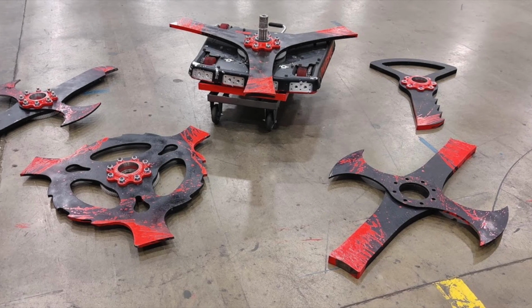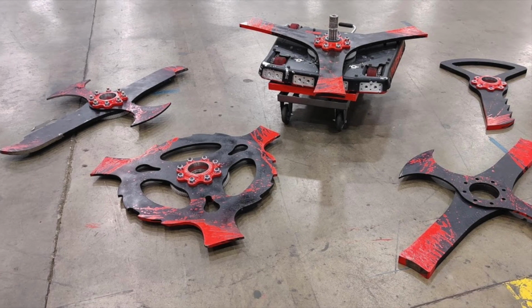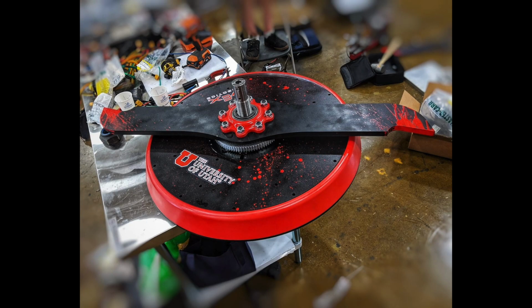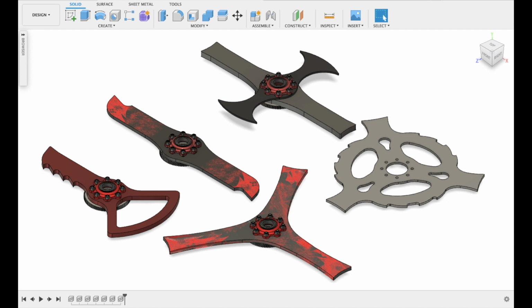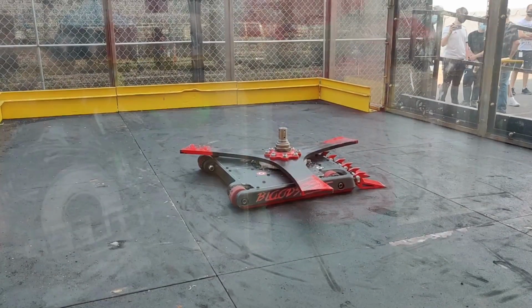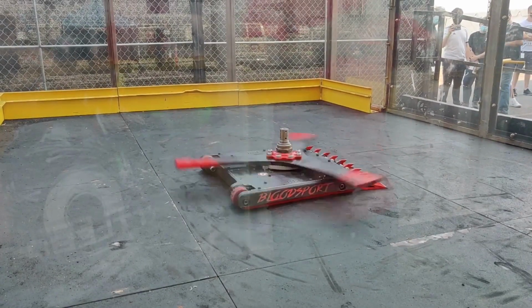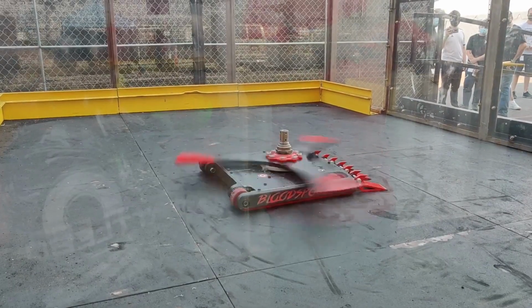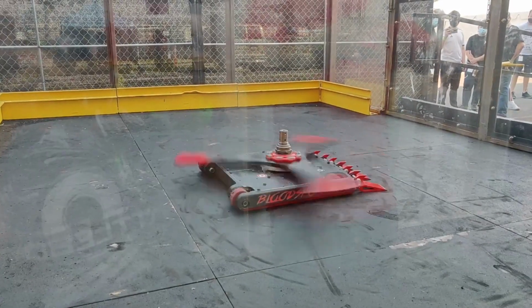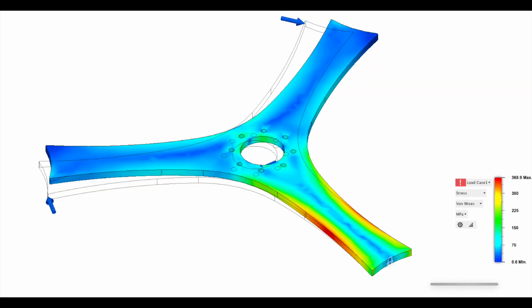Another factor here is our weapon geometry. Our weapons are large and have complex shapes compared to simple bars that have been proven successful in the past. These newer weapons were heavier than our old bar, and weight was devoted to increasing inertia and stability rather than strength. The tri-bar in particular carried about 40% more kinetic energy than the original long bar, while also having 3 narrower arms instead of 2 stronger ones. Interesting is that the tri-bar didn't break where the simulations predicted its max stress would be, but these static stress simulations can only tell us so much.